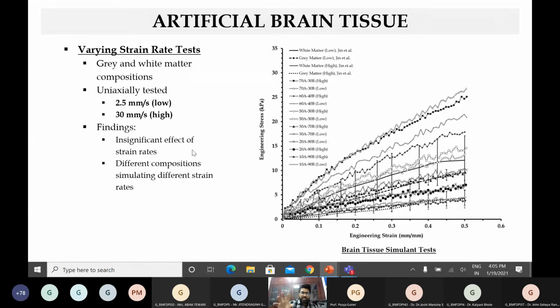Some of the key findings which we saw were that our specific artificial synthetic tissues have an insignificant effect of strain rates just because they're isotropic. They do not have fibers embedded within them. So the effect of strain rate is not really significant in this kind of aspect. However, in an actual tissue, we see a lot of effect of strain rate because of the alignment of fibers after a certain strain value. So we found that our tissue is very different from the actual tissue from a strain rate standpoint.